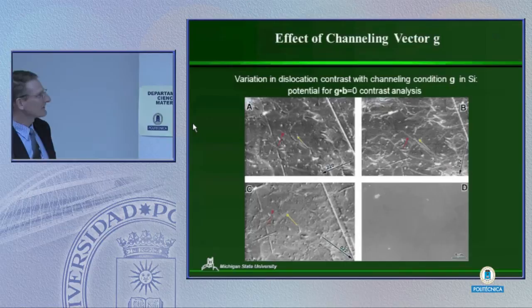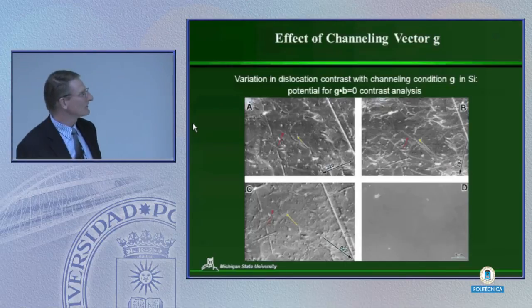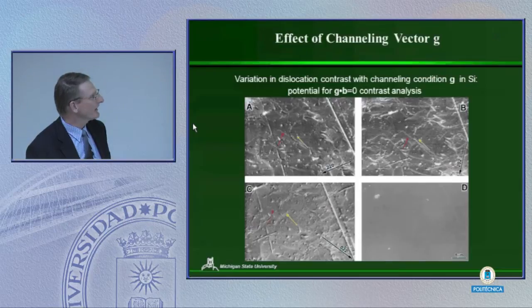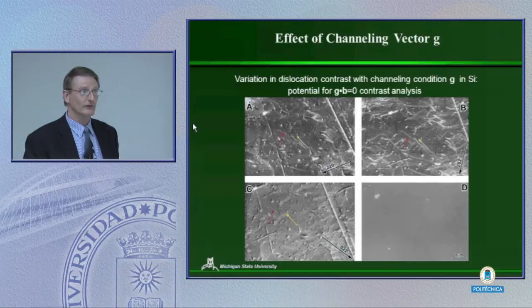And again, here's an area where this is a secondary electron image. These are dislocations in silicon here. And the critical thing is you can see there are changes in contrast with these different dislocations as we tilt to different channeling conditions.